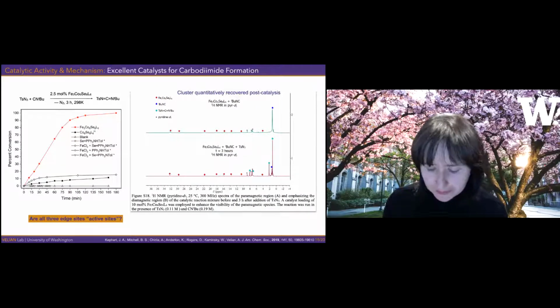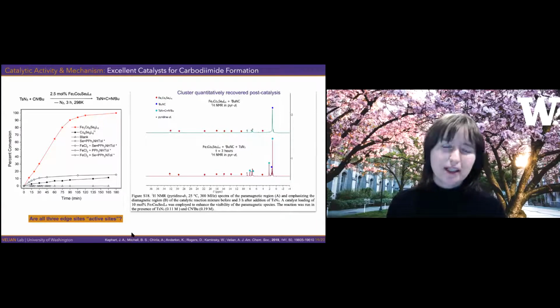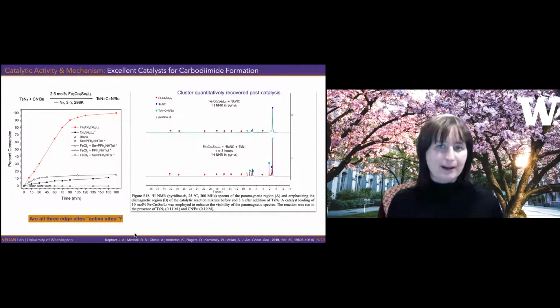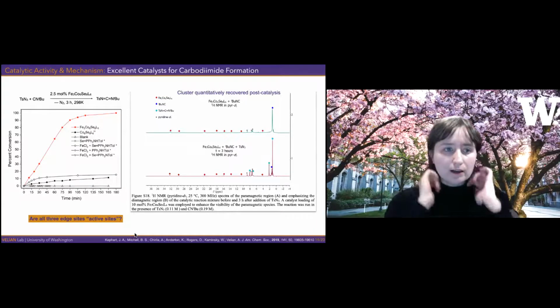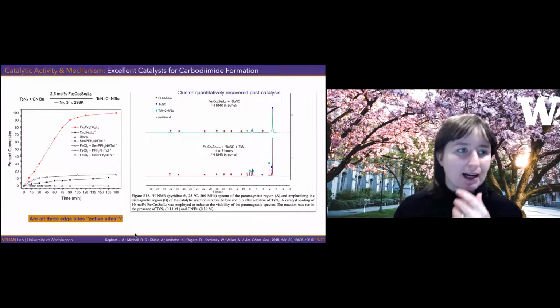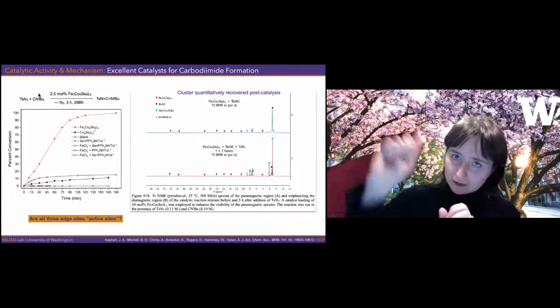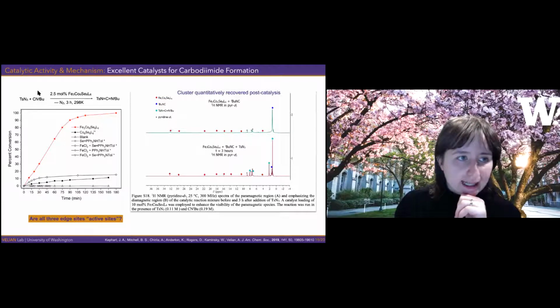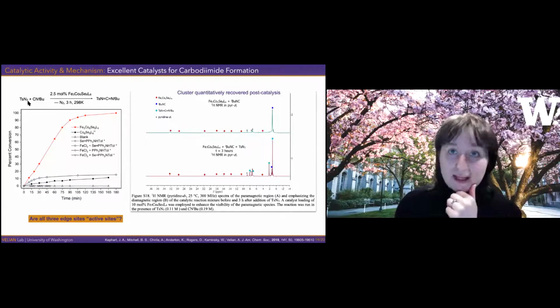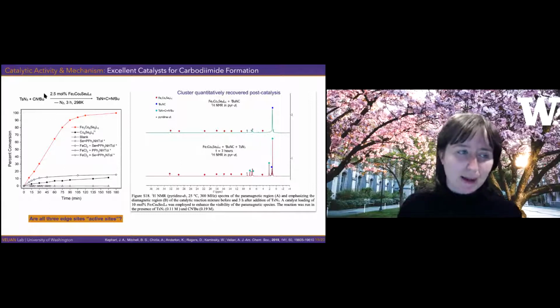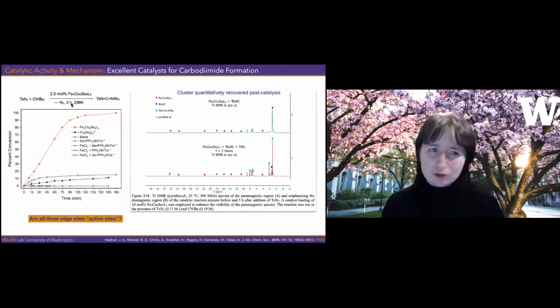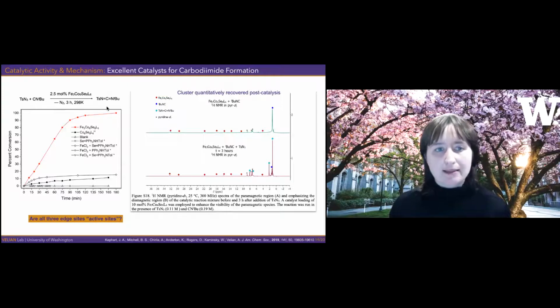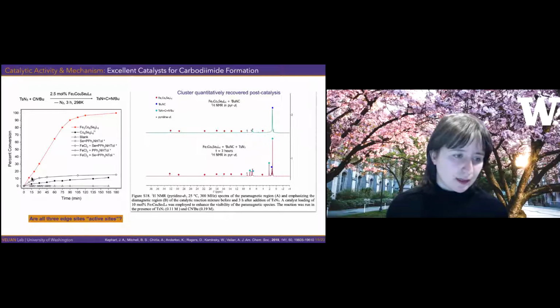But I wanted to segue into telling you that these edge sites are in fact catalytically active. What we've looked at thus far is the activation of azides with isocyanide. You might remember the iron was coordinated in its neutral state to isocyanide, and it was because of this transformation that we were interested in it as a ligand. It's a nice way to follow spectroscopically what happens, but it turns out the tri-iron cluster is an excellent catalyst for this transformation. It happens at room temperature in just 3 hours, and out comes this carbodiimide, which is not an unvaluable product in itself.